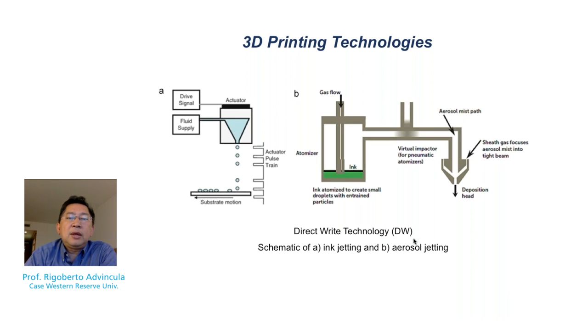Similar to this, with less viscous ink, is direct write technology, almost similar to your two-dimensional printing, except that you build the material up again, because as you deposit it, a curing or thixotropic behavior is achieved, building layer upon layer of the delivered ink. And in this manner too, one can use aerosol materials, basically spray jetting the material on top of another. And again, with sufficient yield stress and curing behavior, one can build your three-dimensional object.